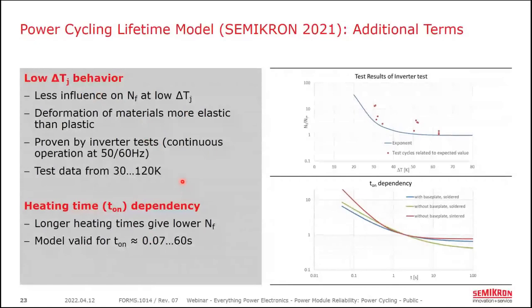So looking at this power cycling with a low delta T, so a small temperature swing. If you thermally model, for example, a fixed speed motor drive, you'll find that the junction temperature is actually oscillating at the fundamental output frequency. So maybe 50 or 60 hertz for a fixed speed motor drive. And depending on the load or cooling configuration, that delta TJ might be 5 or 10 degrees Kelvin.